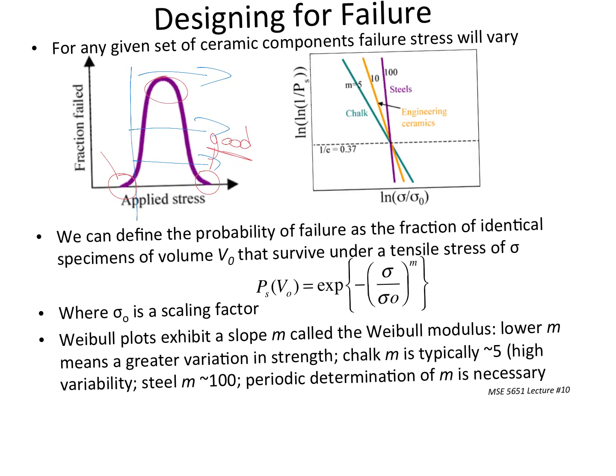So for specimens of volume V0 that survive under external tensile stress of sigma, we have this PS equals this EXP value, where this sigma sub naught is not actually a stress, it's a scaling factor. And these exhibit a slope m, which is called the Weibull modulus. If we have a lower m, that means we have a greater variation in strength. Chalk, which we don't have anymore in here, is typically about 5. Steel is more like about 100.